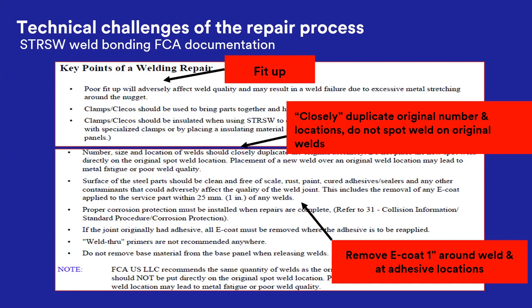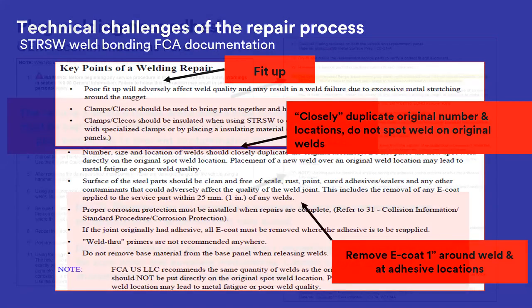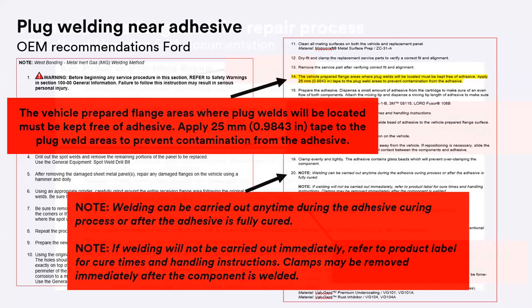The other thing, again, is having that 1-inch buffer area between anywhere you're welding and where you're bonding. So if you're bonding in a sail panel, up around that sail panel area where you're going to weld, leave that 1-inch gap between where you're welding and the adhesive. And in that 1-inch gap, you should also have some weld through primer for corrosion purposes. But don't put your adhesive all the way up to where you're welding. It's going to cause a disaster for your welding and be a big mess. So that's also typical here, and this is information by Ford that's kind of talking about the same thing, using that 1-inch gap between any weld zones.